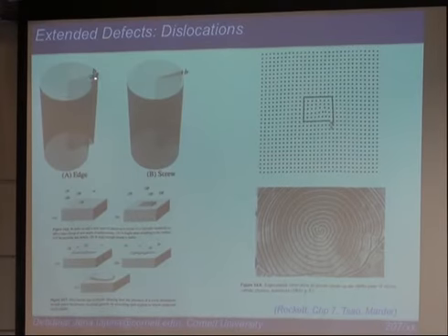And what you'll notice is in the edge dislocation, these are all broken bonds all along the line. In the screw, just one here and one there. Everything inside looks perfect, with little strain and all that. So what we'll see right away now is that this has a lot of energy as compared to that, because there are a lot of broken bonds here, compared to the screw. Not only that, we'll see that the edge dislocation has a very strong strain field surrounding it, whereas the screw has almost no strain around it. It's a very, very low energy defect. We'll see that now.